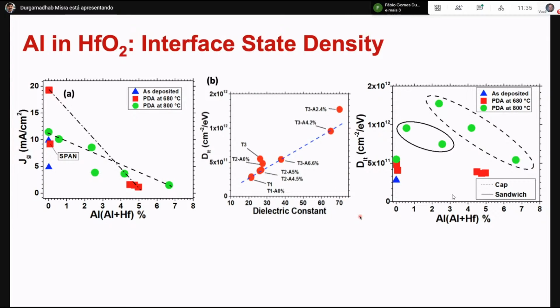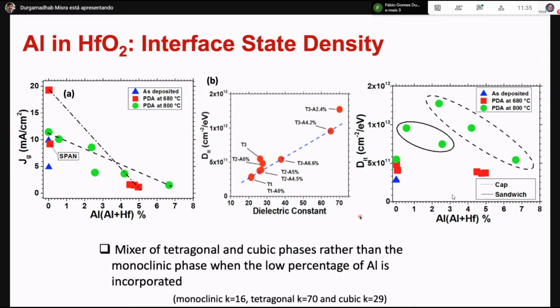So you can go to orthorhombic structures, and from the tetragonal to cubic phase, and sort of different crystallization of hafnium oxide gives different dielectric constant. So if the crystallization is heavy, then dielectric constant goes up. But it doesn't really solve the problem of leakage current and also interfacial defect. So we have to optimize both. You can have some crystallization, but if you have a polycrystalline hafnium oxide, then it has large leakage current. So these are certain issues we looked at in the aluminum and hafnium oxide.